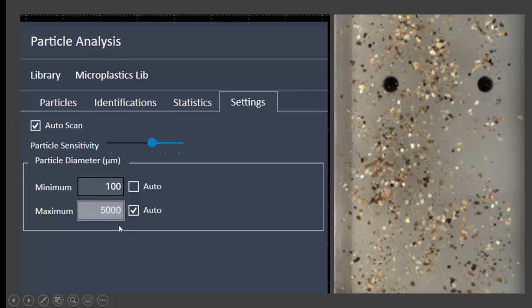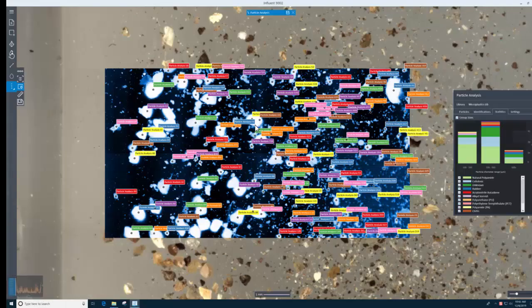We then select the sensitivity. For this slide, this is an influent sample, so I've only selected to analyze for particles larger than 100 micron and smaller than 5,000 micron. Now, if we were looking at effluent samples, we may change this to look at particles from 20 micron up to maybe 300 microns. This was material obtained on a 500 micron sieve, and this area under analysis probably took roughly an hour to analyze, and it's probably about 1/6 of the slide. And you'll see the number of particles that were analyzed and identified on this.